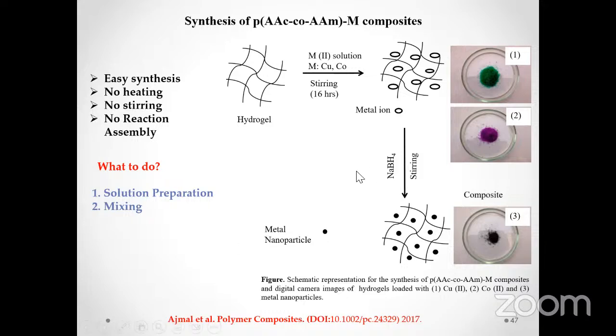And this was a bulk polymerization. In this bulk polymerization, we've just mixed the monomers in a simple beaker with initiator, and then an accelerator, which is responsible for the redox reaction and generates the free radicals even at low temperature, and the reaction can be carried out without any high temperature requirement, without any nitrogen atmosphere, and at low temperature we have prepared our hydrogel system. And that hydrogel system was also effectively used as a reactant for the synthesis of different metal nanoparticles, as in this case we have prepared copper and cobalt nanoparticles.